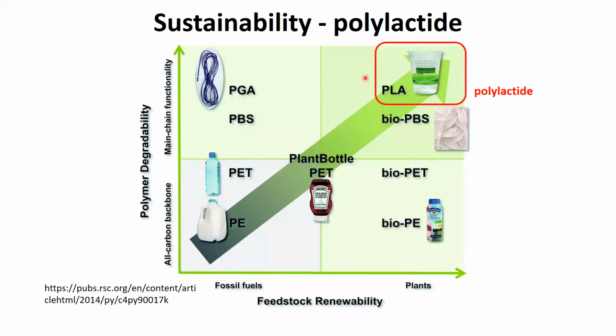And one of the reasons we like polylactide, and that sits up here, and this is a nice matrix that talks about how degradable the polymer is versus how renewable the feedstock is. So polyethylene is here, which is basically fossil fuels, all carbon backbone, very low feedstock renewability. Polylactide is right at the other extreme, where we have some main chain functionality, so we have very good degradability, and the feedstock is from plants. This is the area we like to work in and the material we like to use.